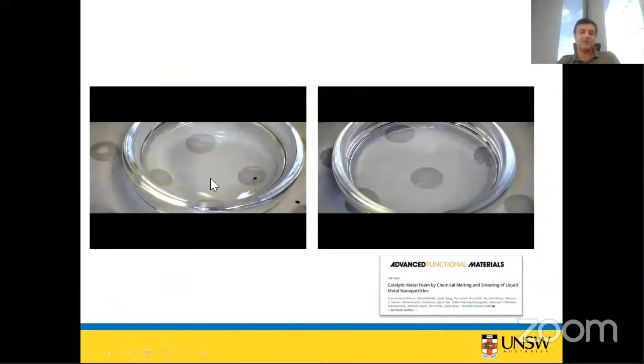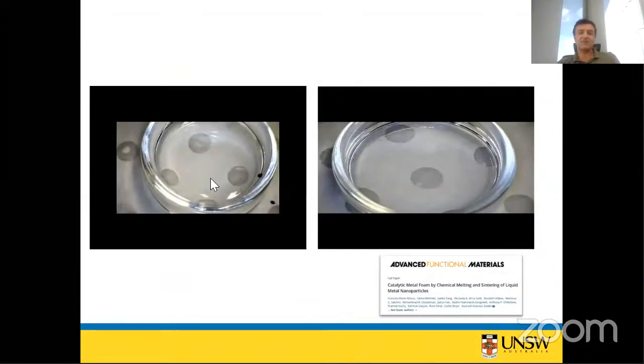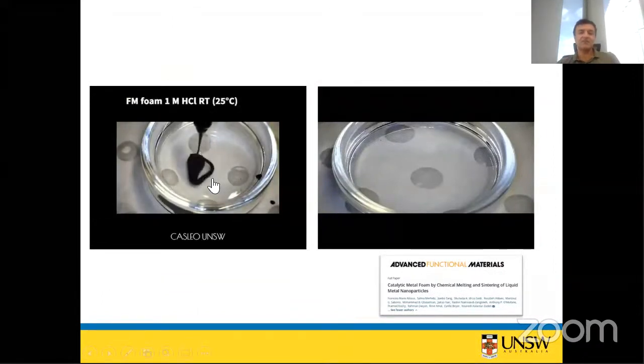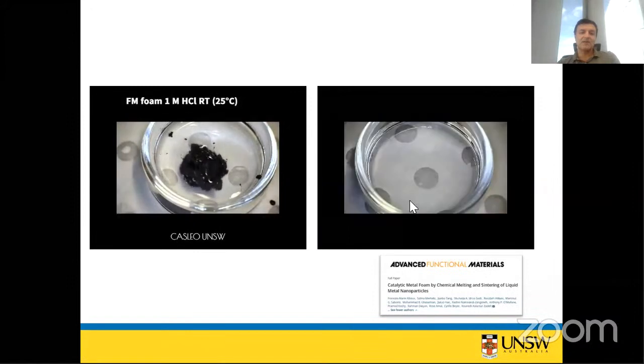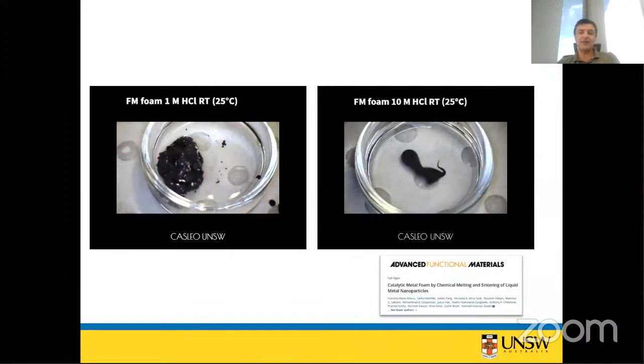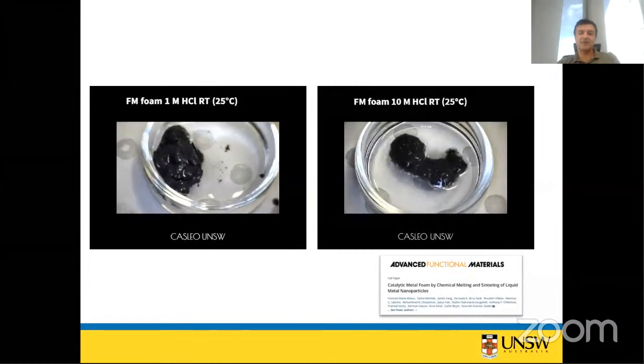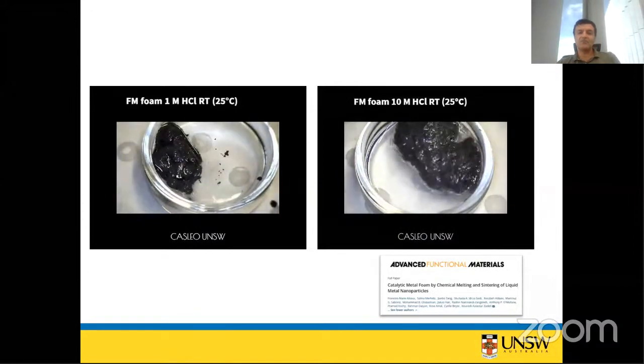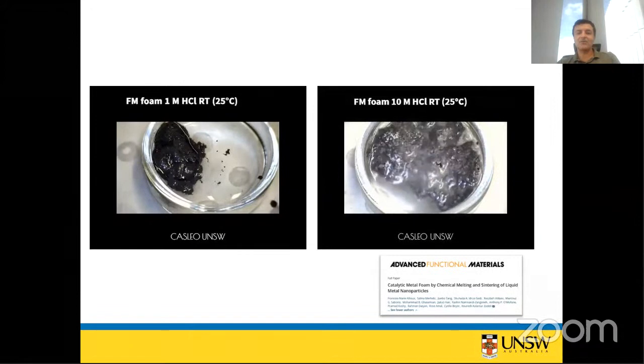So here it is how it works. You put a different concentration of acid. If acid concentration is only one mole, foaming happens very gradually. If the acid concentration is high, foaming happens very rapid. This is 10 mole. So from a very small droplet, you get this foam that covers the whole beaker.